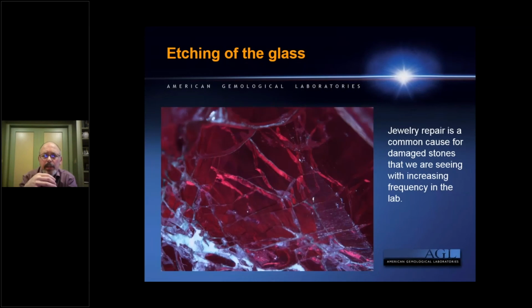When we look a little bit higher, we can see these reflective ribbons, which just show that the alteration and the removal of the glass, the etching of the glass, is only taking place to a very shallow penetration. These are fractures which are extending all the way through. So even with as bad as this stone looks now, the way it's been damaged, still only part of the glass has been removed.